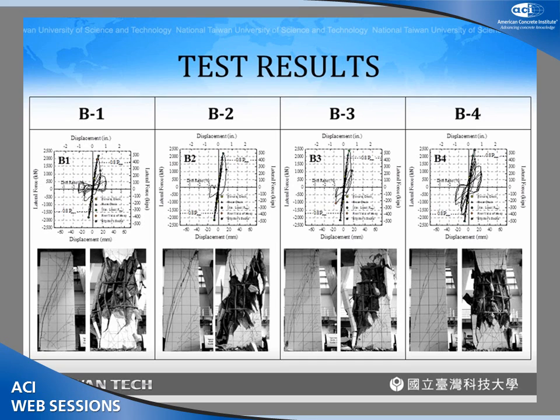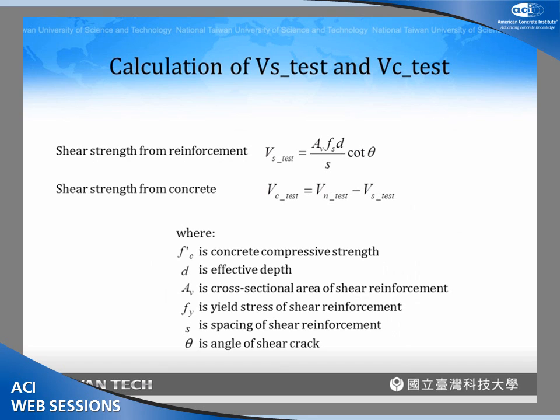When we increase the axial load, the behavior becomes more brittle. The drop of the shear strength becomes more rapid. And we also found that the shear crack angle reduces when you increase the axial load.